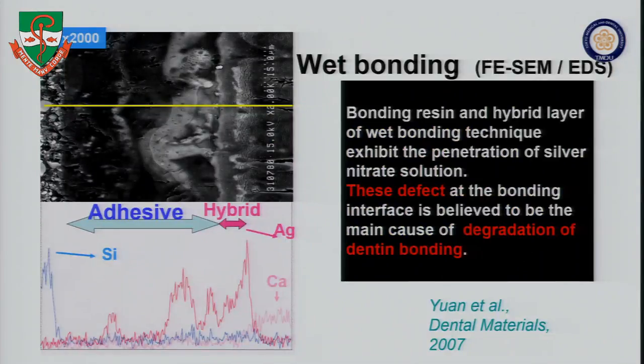In the case of the so-called wet bonding technique in the etch and rinse technique, we try to evaluate the weak point at the bond interface. This is the composite resin, and this is the bonding resin layer, and this is the hybrid layer, and this is dentin. We immerse this kind of specimen into the silver nitrate solution for one night.